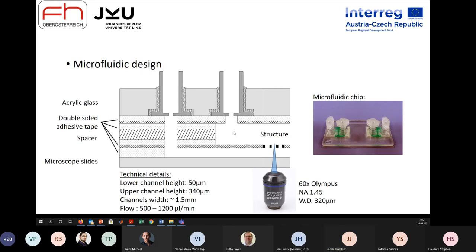Good. So now to the microfluidic, this is how it looks. We had this first channel, second channel, then we had the objective here for illumination. The building of this channel was quite a challenge because the working distance of our objective is only 320 micrometers, which means this is the distance between the lens and the focus, with respect to the glass slide. So we needed the lower channel especially to be very flat, and these were the two inlets of the microfluidic, and here you see the membrane, and this was of course the structure.